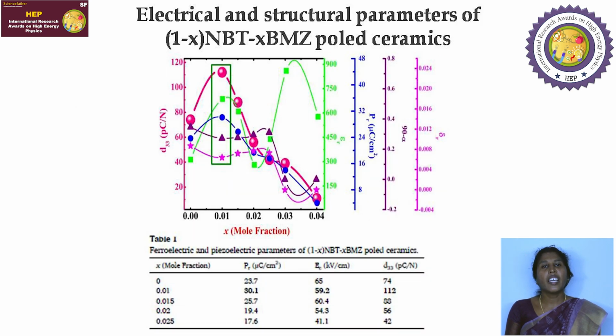This figure shows the electrical and structural properties. We can relate the electrical and structural properties. The left y-axis gives the piezoelectric coefficient, that is d33. On the right, we can see 4 y-axes. The first is related to the dielectric constant. The second is related to the ferroelectric polarization. And the third and fourth are related to the structural parameters, that is 90 minus alpha, known as rhombohedral lattice distortion, and delta R, which is known as lattice strain.